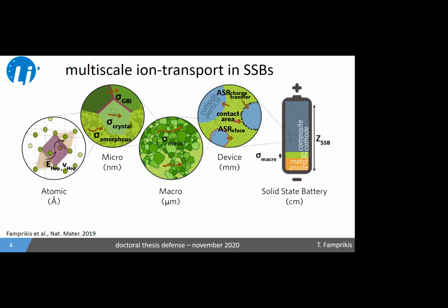So you will have crystallites with preferential orientations, you will have grain boundaries that can have their own resistances, you might have amorphous phases, impurities, and the distribution of all of these in space will give rise to this mesoscale conductivity. In addition, when you're trying to contact your electrolyte with electrode materials, you're going to have an issue that does not exist in lithium ion, where the liquid electrolyte can simply wet all the solid parts. So you're going to have problems of contact area.